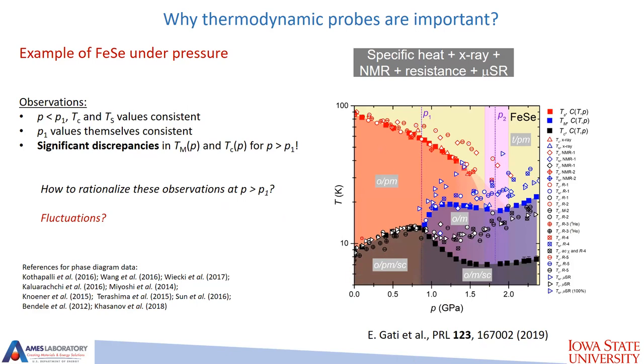In this material, up to P1, which is the pressure when magnetic order appears, whatever you measure, transport, thermodynamics, phase lines are exactly the same. However, beyond this point, when there is superconductivity and magnetism and leftover phase transitions, transport and thermodynamic measurements give you a different position of phase lines. We thought it was related to fluctuations. Again, please read more if you are interested.